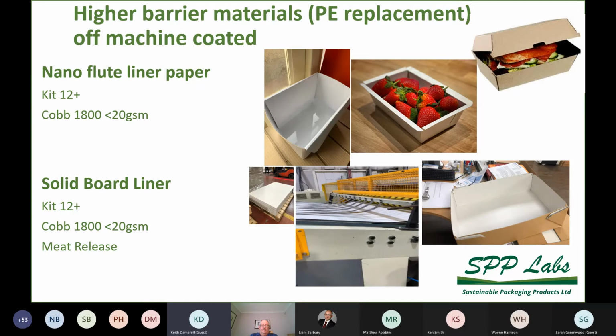We can achieve very high grease resistance by the old method of kit 12 plus, and very high levels of water resistance. We measure water resistance now with the Cobb test, but instead of 60 seconds, we do it with 30 minutes, and we get values below 20 grams per square meter for 30 minutes. There's an image there of a barrier-coated liner paper produced as a solid board, which is used generally for meat packing. You can see liquid water in there, and it can hold that liquid water for over 4 days. So those are being produced and achieved today.